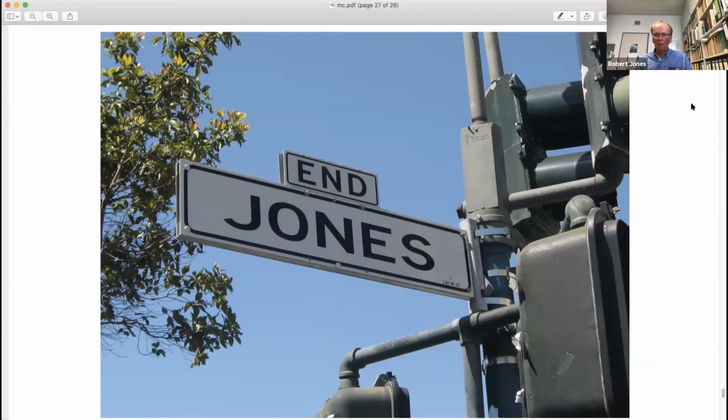We also found the following. For example, we took 3 samples that were identical, at the same temperature, 600 Kelvin, but we had a different distribution of velocities to bring it up to an average temperature of 600. And amazingly enough, these materials all crystallized, but they crystallized at different times. The same structure, but with a different heat bath, if you wish. It was perhaps not surprising. It's a stochastic process that you have to understand, but it was very frustrating to watch the ones that were not crystallizing, waiting until something happened, and then it went fairly quickly. In other words, there's a lot of things going on there that it's very difficult to pin down.